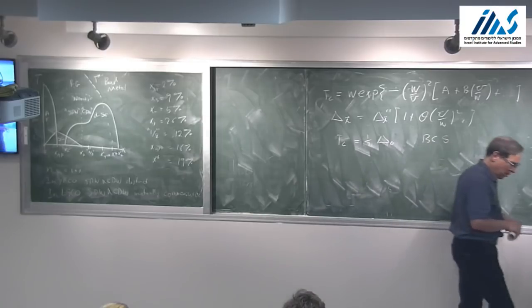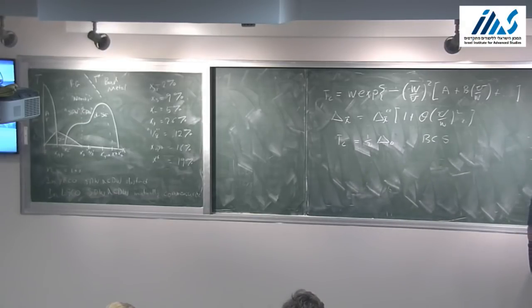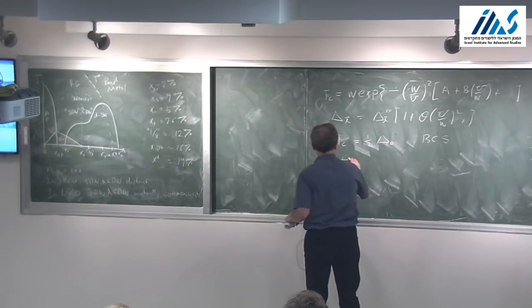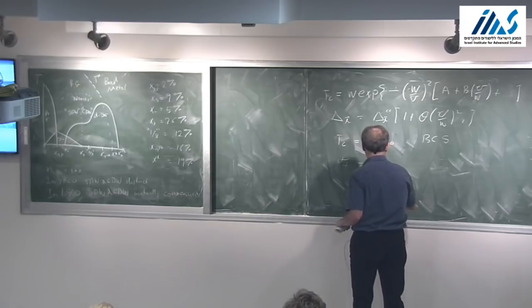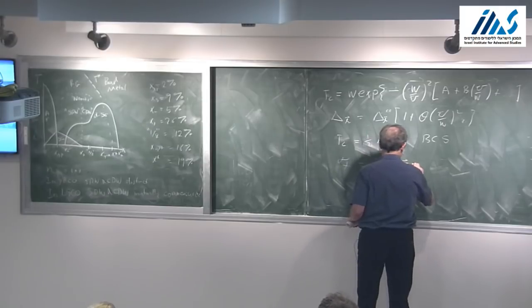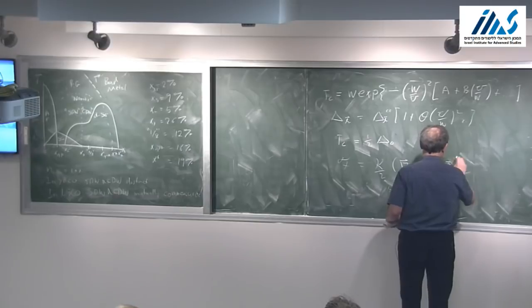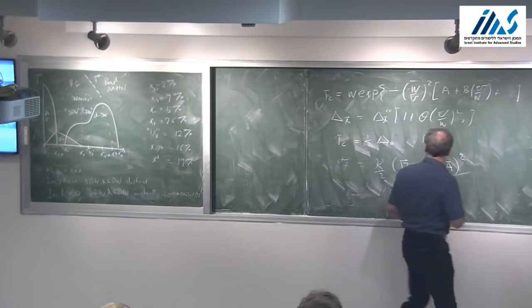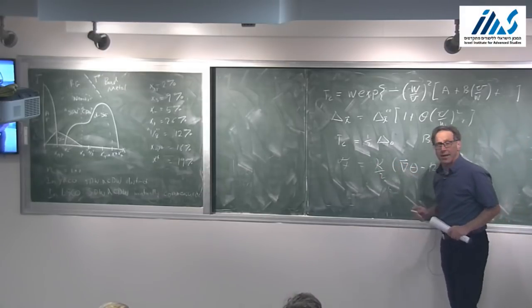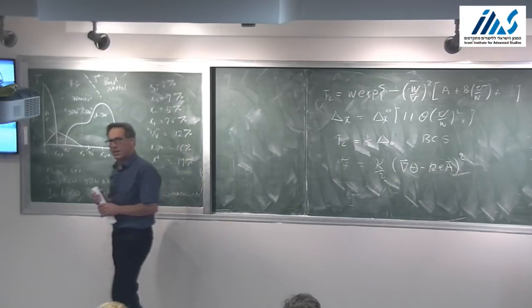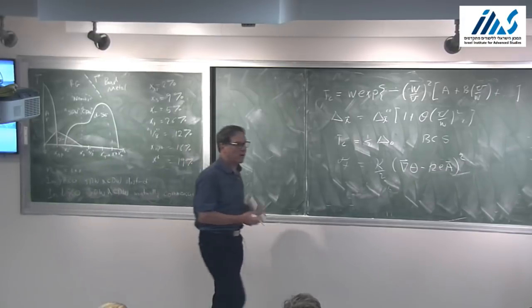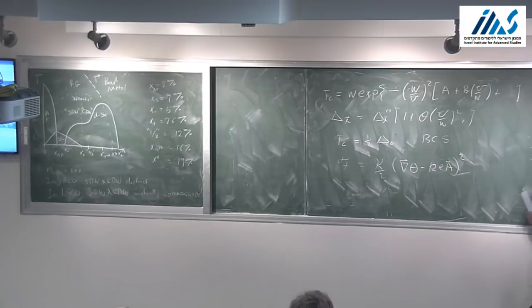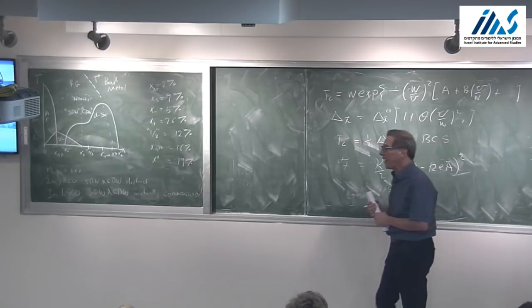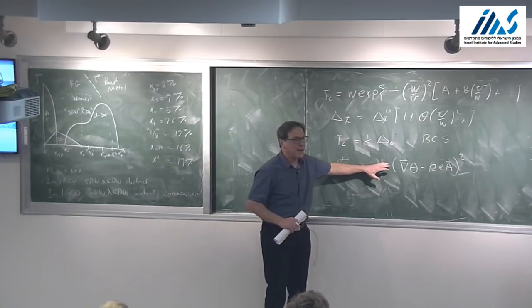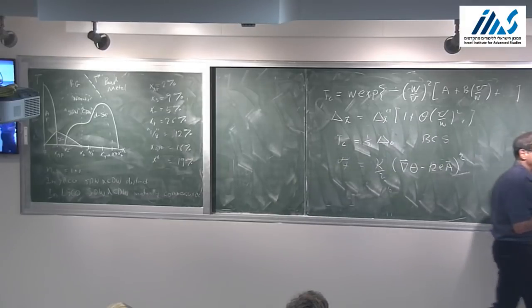Now, there's another number that characterizes the superconducting state, which is the superfluid stiffness. There's a term in the effective free energy, trying to write down something gauge invariant so I don't get killed, of this form. And the existence of a non-zero superfluid stiffness is one of the characteristics. In fact, in some ways, it's the most fundamental characteristic of the superconducting state. And so what one can see is, at least taken as a classical effective Hamiltonian, this superfluid stiffness is what governs the fluctuations in the phase of the superconducting order from one region of the sample to another.